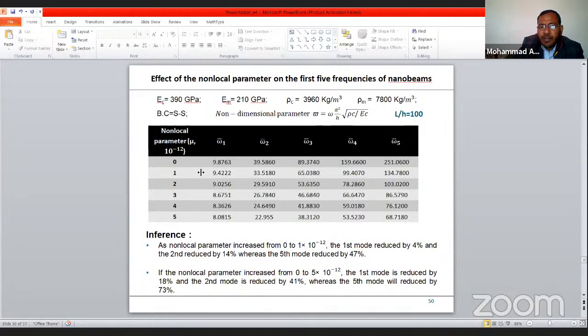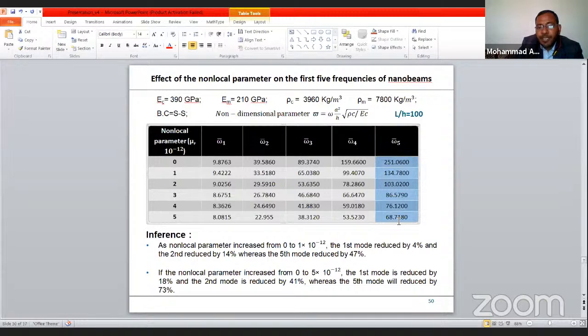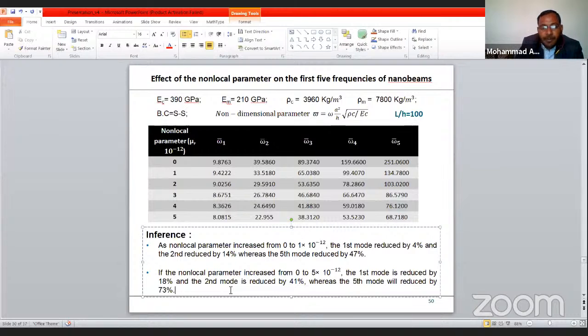observed that on increasing the non-local parameter, the frequency parameter is decreasing with the increase in the non-local parameter, but it has significant effect for the higher mode, like for the fifth mode. When we increase the non-local parameter from 0 to 5, it means the frequency gets reduced by 73%, and for the first mode, the reduction in the frequency is around 18%. So based on this result, we can conclude that the effect of non-local parameters also depends upon the mode of the frequency.